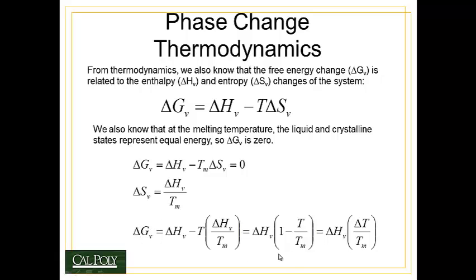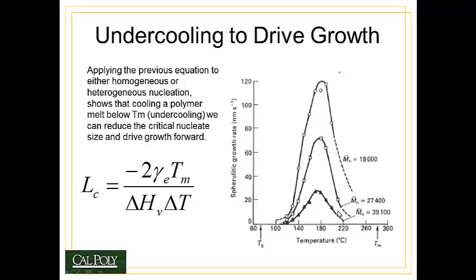If I plug this term in for entropy, I get this equation here, which can then be solved and suggest that the change in free energy of the system is equal to the change in enthalpy times the change in temperature divided by the melting point. And this is what's important.